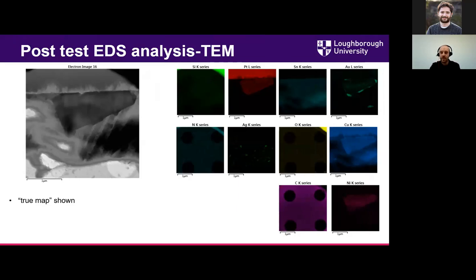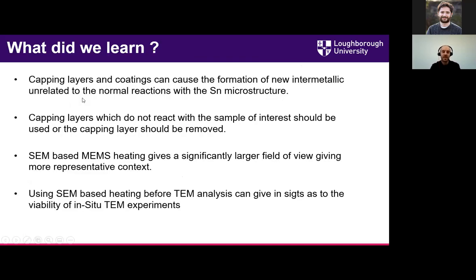I think this was just to show that the coatings that we use have a serious effect. Some of the precipitates formed, like the gold precipitates along this precipitate here, were from the surface coating on top of the sample, so we have to be quite careful. Capping materials and coating layers before we perform in situ heating are really quite important. We need to make sure that none of those are going to interact with the sample of interest.